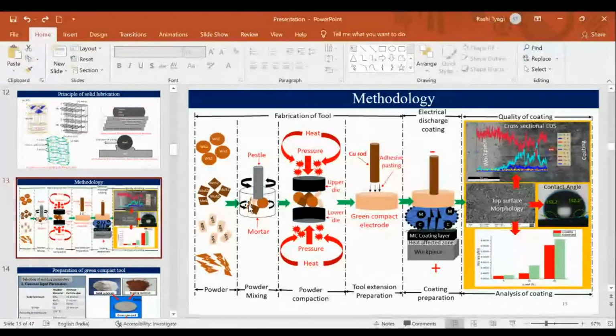A mortar and pestle means there is a mortar and there is a pestle; when we put the powder in the mortar, we move it around with the pestle. For uniform mixing, we mix these powders so that they get properly mixed. We performed this operation for 2 to 3 hours to check whether it is uniformly mixed or not.